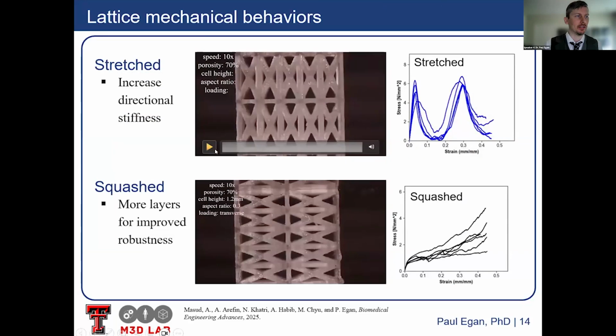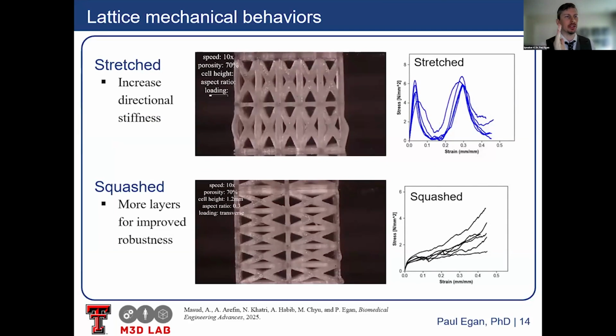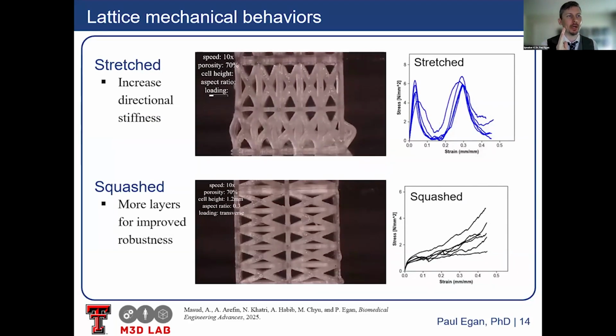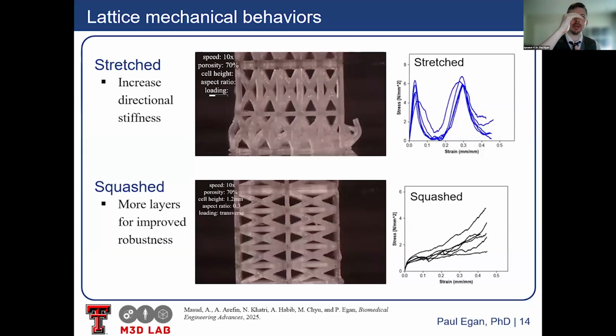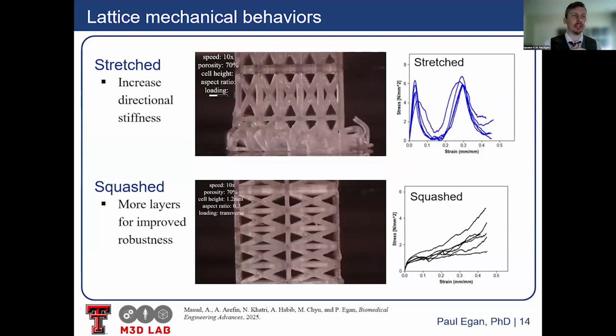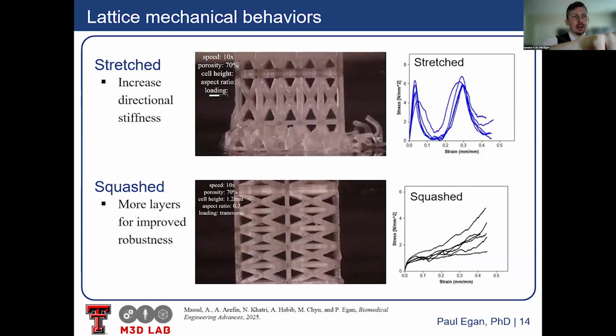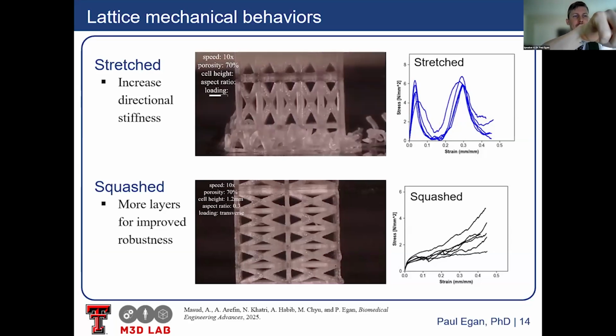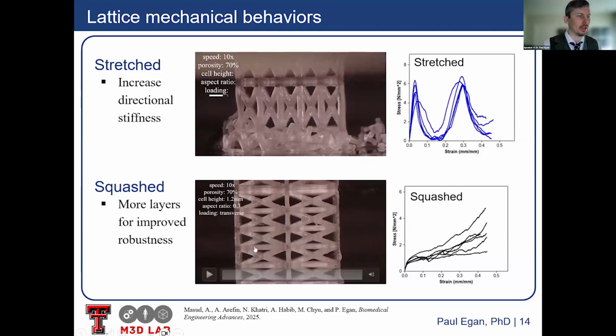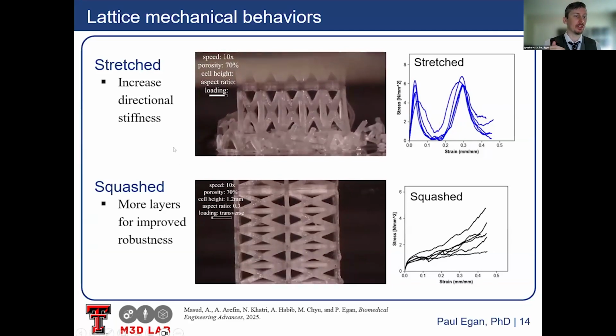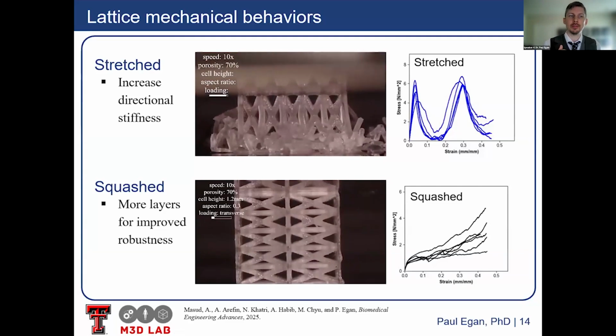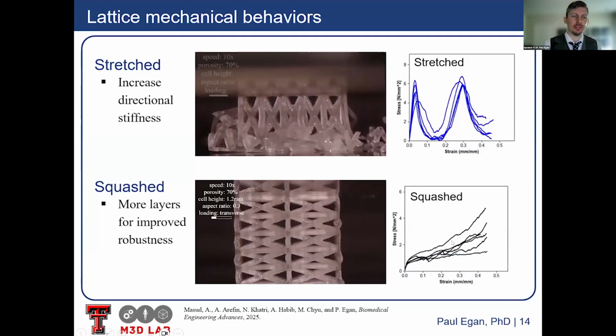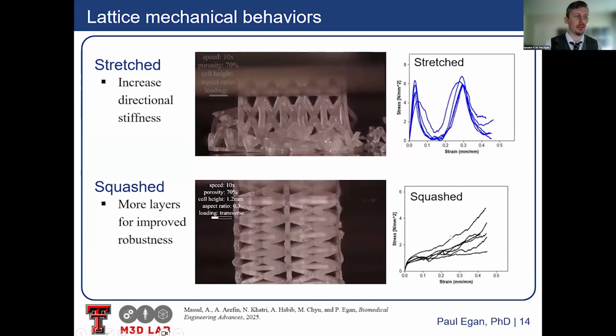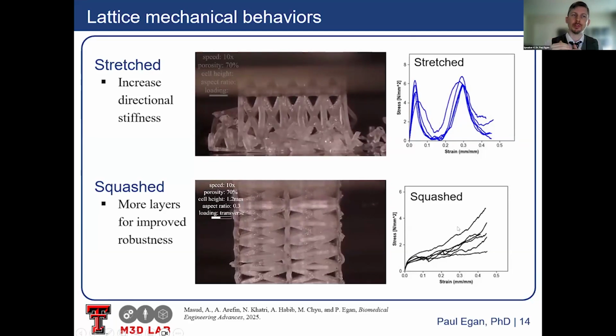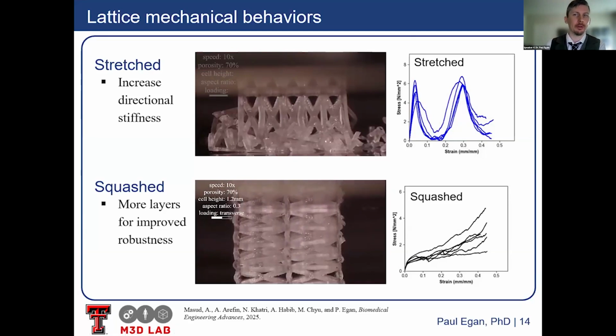In some of our mechanical testing results, we have a couple of videos here. So this is with the stretched unit cells. What you're going to see is these tend to fail and deform in buckling. So there's a limit to how long you can make those beams before it's going to fail very easily in buckling. And so you can see on the response, it has a high elastic modulus before its first breakage point. Whereas if you tried the opposite strategy with squashing the unit cells, you get a more consistent elastic modulus, so stress-strain response over time, but it's weaker overall. And that's because you have more smaller cells in parallel, in series there.